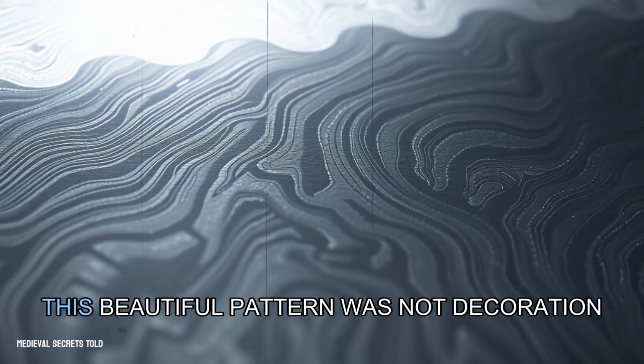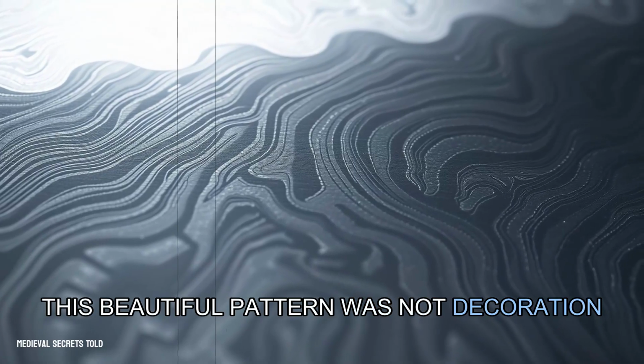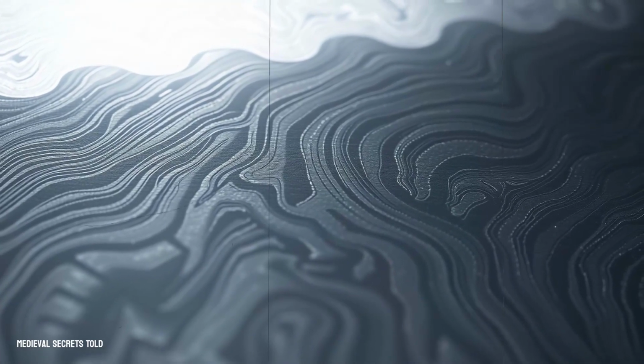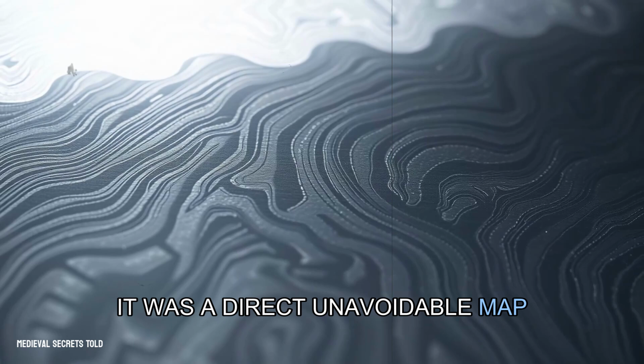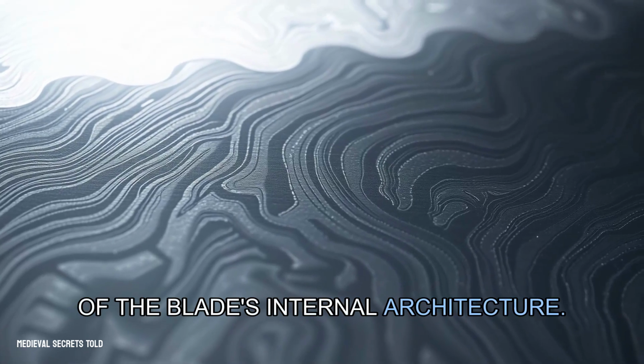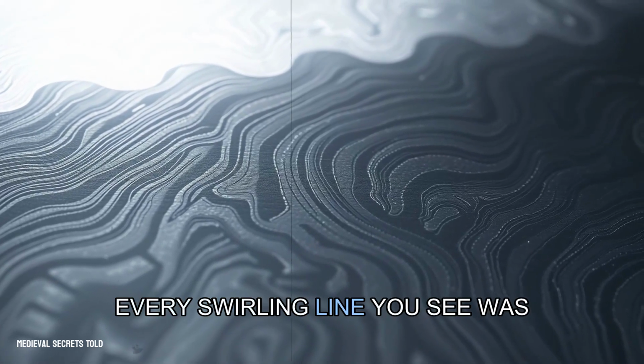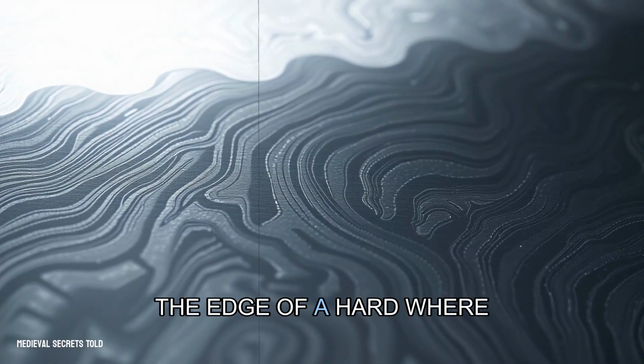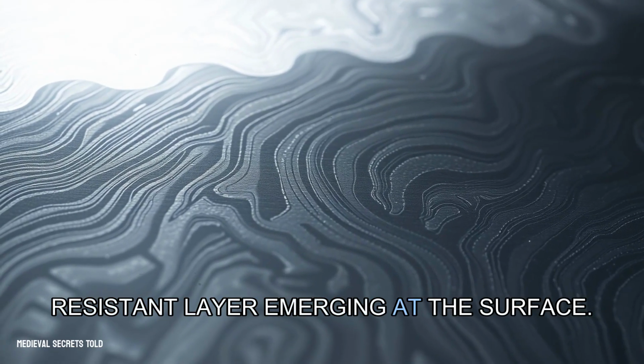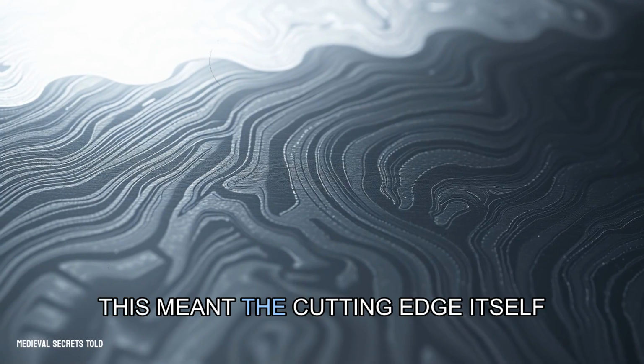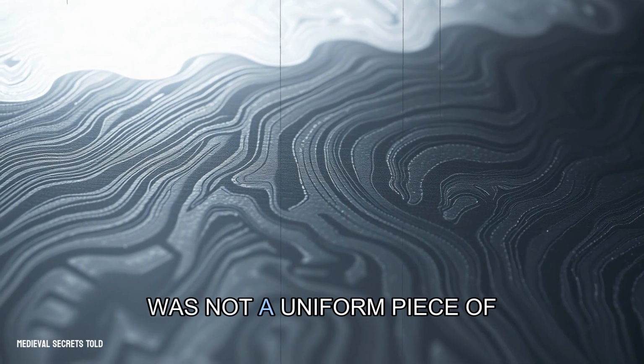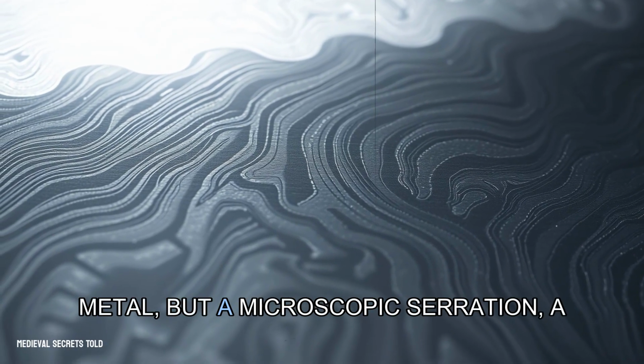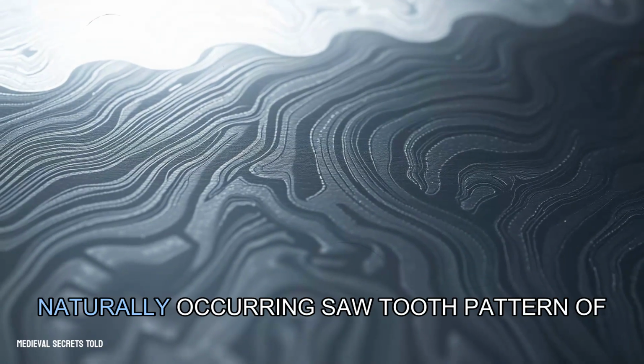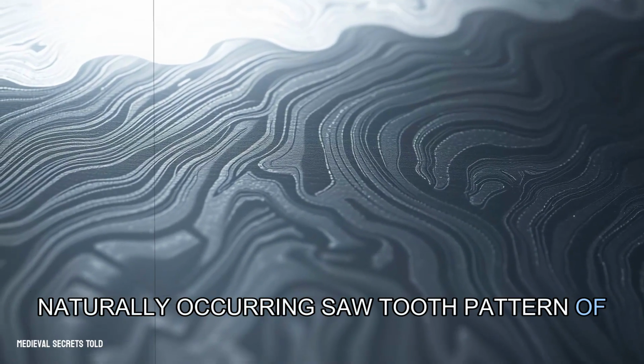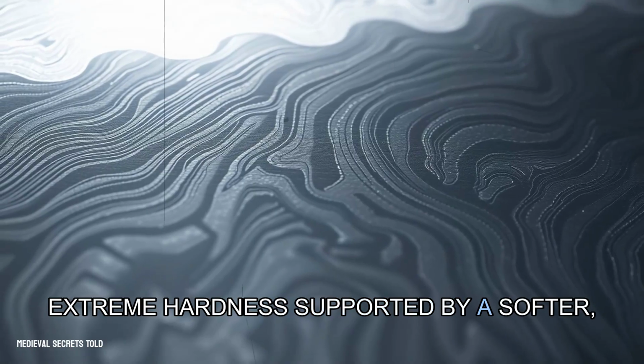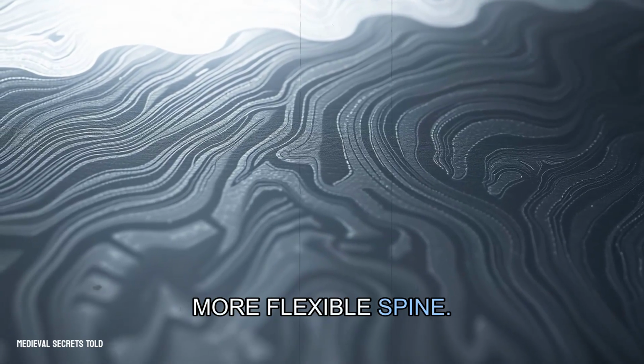But here is the crucial point every viewer must understand. This beautiful pattern was not decoration applied on top of the steel. It was a direct, unavoidable map of the blade's internal architecture. Every swirling line you see was the edge of a hard, wear-resistant layer emerging at the surface. This meant the cutting edge itself was not a uniform piece of metal, but a microscopic serration, a naturally occurring sawtooth pattern of extreme hardness supported by a softer, more flexible spine.